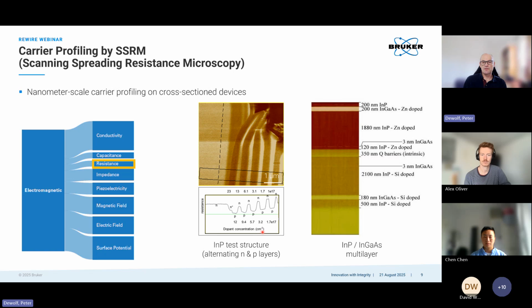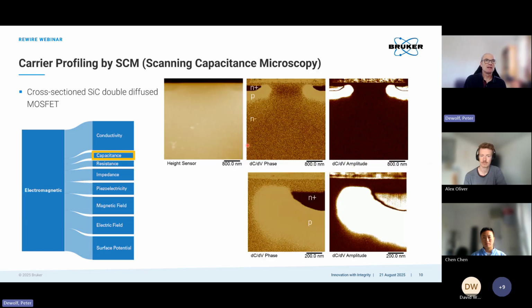Second, in terms of carrier concentration sensitivity, this is a test structure with multi-layers, and every second layer the concentration changes by a little bit. Like these last two steps here, for example, the N-type doped is 1E17 and 1.7E17. That difference, which is relatively small, can easily be detected by this technique. Same with the P-type concentration levels - it gives you a feel for resolution and concentration sensitivity.